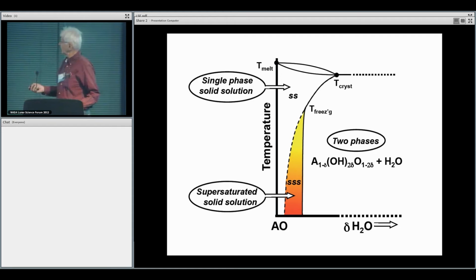At the high temperature, the amount of water is highest, and then as you cool down, it forms a solid solution of a compound AO with some of the hydroxyl. And in order to incorporate the hydroxyl, you would, for instance, leave out cations in order to achieve balance. And therefore, when it cools down this way, sooner or later there will be kinetically inhibited freezing, and you enter a regime that we know as supersaturated solid solution. And what you would actually then see on the surface of the moon or on the Earth is a solid solution that you would expect to have hydroxyl.